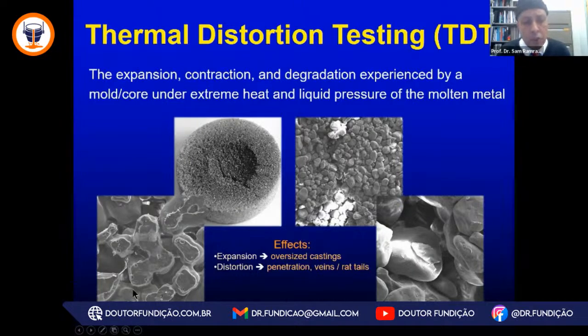For example, here I'm showing you in the picture at the bottom left, a chemically bonded sand after we've taken a SEM, or scanning electron microscopic shot, to show you the binder bridges. I took this picture myself, so I know exactly what is happening. And at the heat affected zone from the thermal distortion test, we have sand losses as seen on the cookie. In this particular cookie, a urethane cold box specimen, the binder pyrolyzed in the darker colors. We lost sand at the crater. This particular image is the actual cookie, and it also shows a crack that has occurred after elevated temperature exposure.